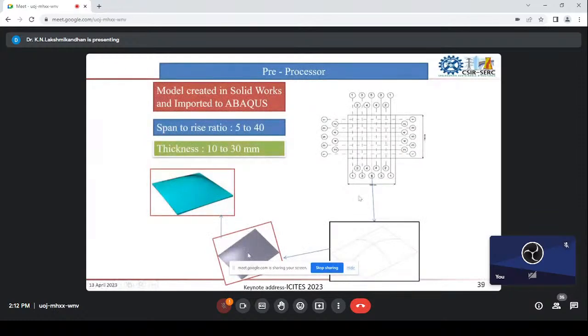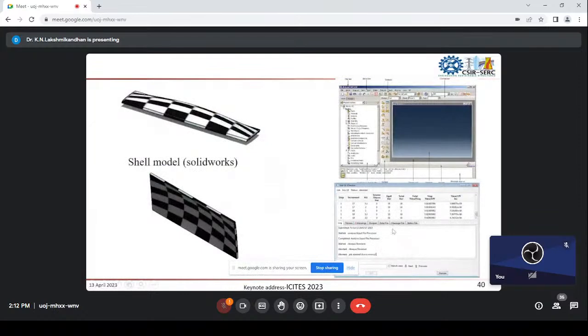So these are the typical ferrocement models we developed using SolidWorks, and from SolidWorks we imported them to Abaqus, and we modeled these particular shells. If you see this, this is the positive curvature, and if you see these edges, there is a slight downward curve. This represents the negative curvature. So the shell itself has both positive and negative curvature, so that the stresses we get from the external loads will be compensated by the shell. That's the way we developed it.